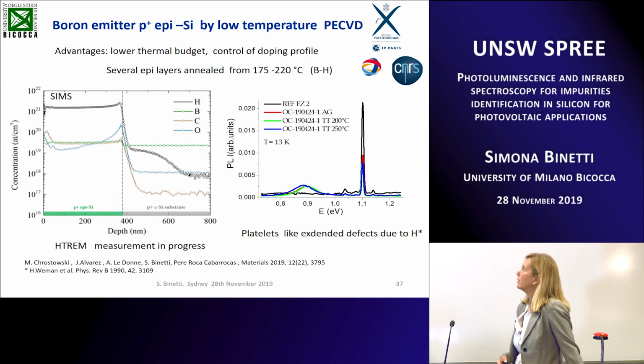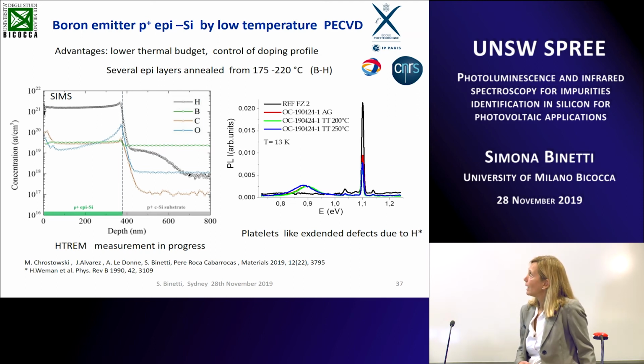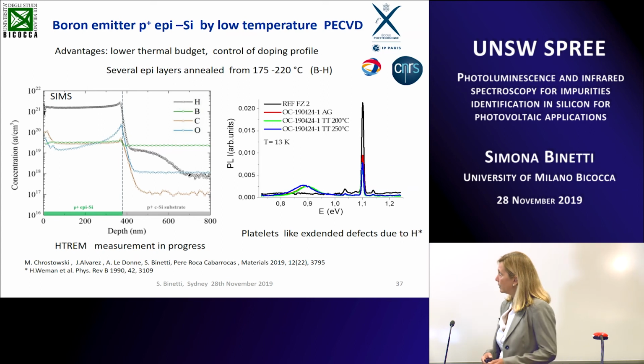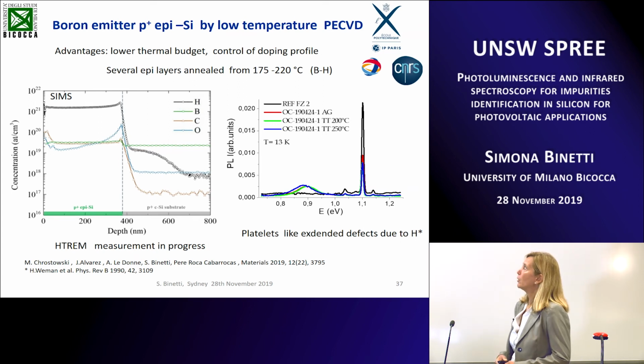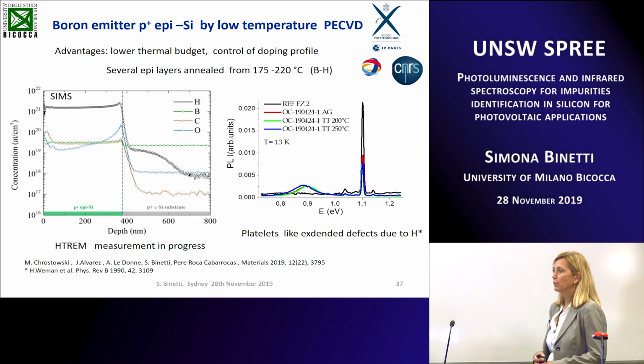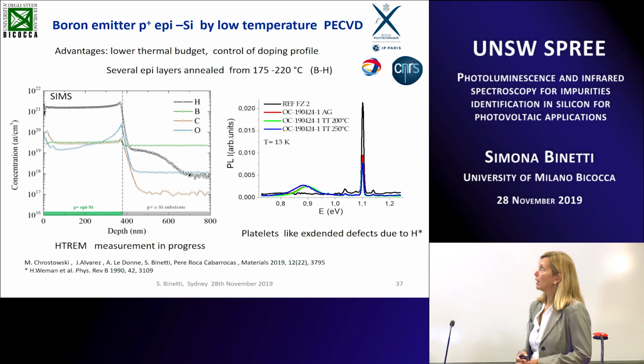Recently, we studied also by photoluminescence, in collaboration with l'École Polytechnique of Paris, the CNRS and the Total Center. They formed a very nice research center in photovoltaics in Ile-de-France, close to Paris. And they studied a new methodology to form a junction. It is a boron emitter, an epi layer grown by low temperature plasma enhanced chemical vapor deposition. The advantage, of course, is a lower thermal budget,